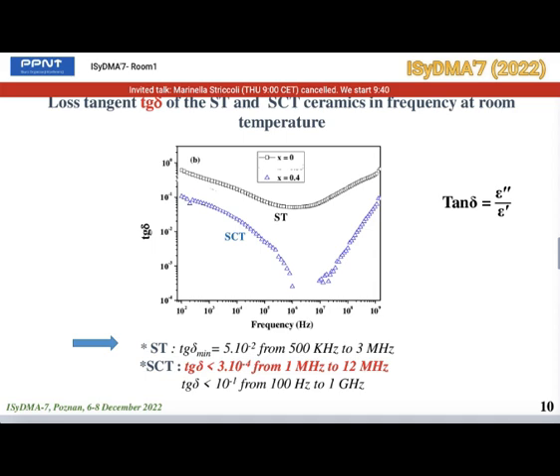Here we have the frequency dependence of tangent delta of ST and SCT ceramics from 100 Hertz to 1 gigahertz at room temperature. We can see that SCT displays a loss tangent lower than 3.10 to minus 4 from 1 megahertz to 12 megahertz, and SCT tangent delta values do not exceed 6.10 to minus 2 at 1 gigahertz, while ST ceramic gives a minimum value of tangent delta equal to 0.05 from 500 kilohertz to 3 megahertz.